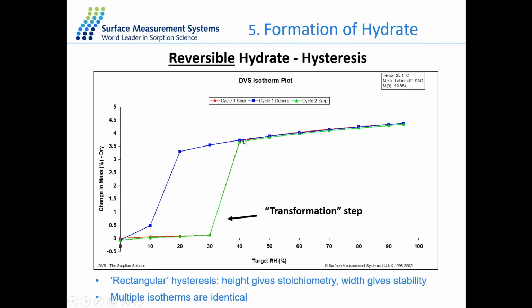And if you have the molecular weight of the sample to begin with, you can then calculate how much water is hydrated inside the material. It's forming a monohydrate or dihydrate or trihydrate, from the shape of this isotherm or the uptake at a certain stage. So this is a kind of reversible hydrate formation.